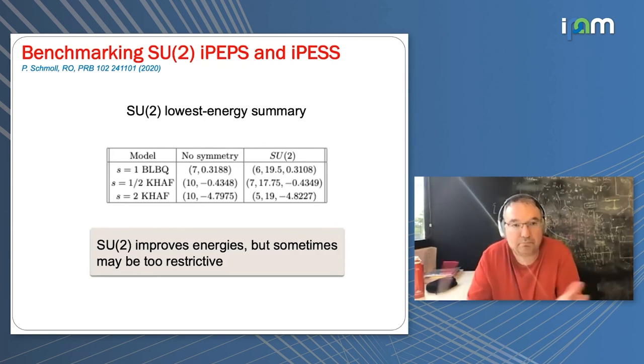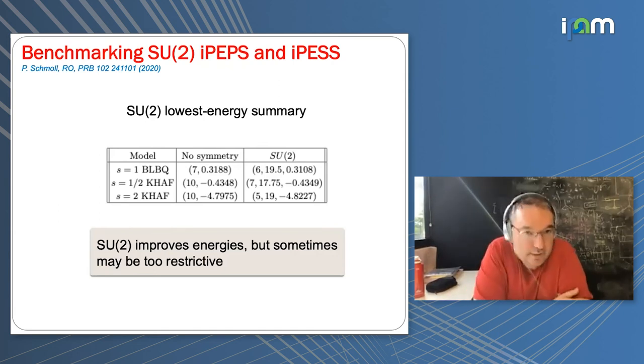The take-home message is that using SU2 symmetry in 2D allows you to reach larger bond dimensions. It allows you to have lower energies. That's systematically what we found. However, it may be that it's over-constraining your ansatz, okay? In such a way that perhaps using U1 symmetry is a better idea than using SU2, depending on the actual model. All right, that's the conclusion that we had.